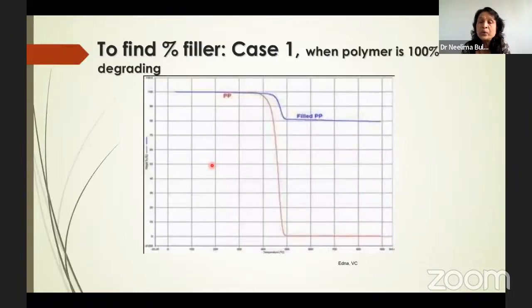Second thing is that I told you that you can find out the percentage of filler also. In the polymer industry, many times manufacturers put ingredients into their sample for the betterment of the properties and for the economy also. If they vary the percentage by 1%, for them it is a huge profit, but for us it is a huge loss, because the percentage of filler is going to affect all our properties: mechanical properties, weight loss, haze, optical properties, and everything.